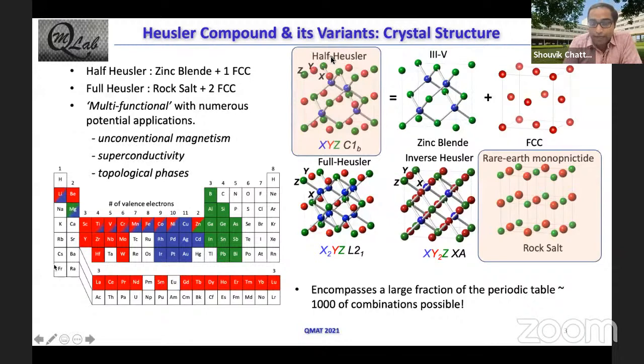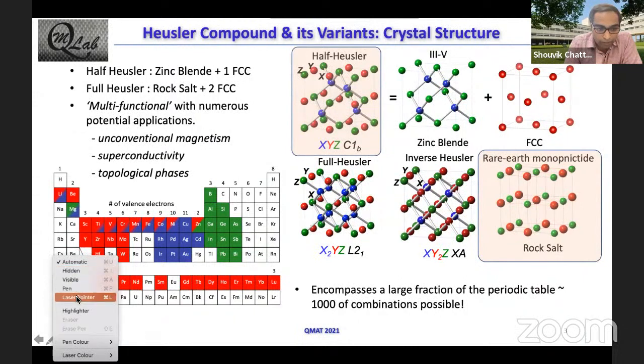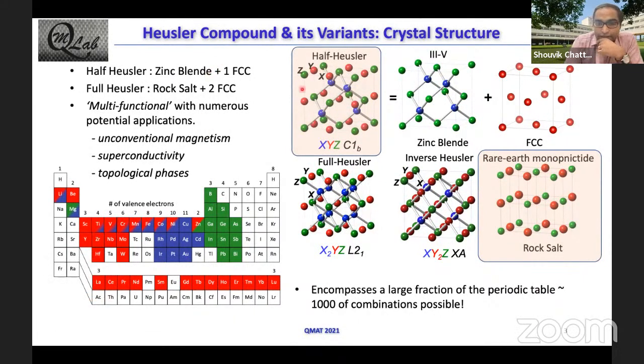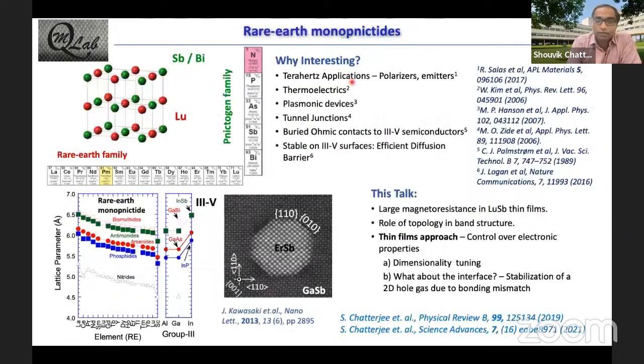And here I'm just trying to highlight the crystal structure. As you can see, you can think of a half-Heusler as a combination of a zinc blende, which is like the structure in regular III-V semiconductors, and an FCC. And if you want to go to the full Heusler, you can think of it as a zinc blende plus 2 FCC sublattices. Now, if you take out all the tetrahedral interstitial sites, what you end up getting is a rare earth monopnictide, which has a rock salt structure. So today I'll be talking about one example, which is the rock salt lutetium antimony, and another, if time permits, of a half-Heusler platinum lutetium antimony structure.